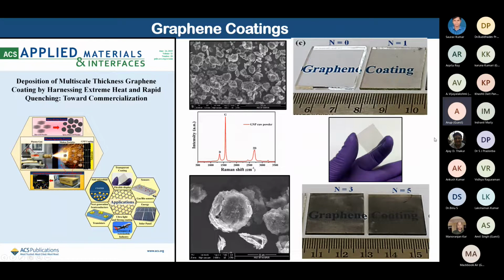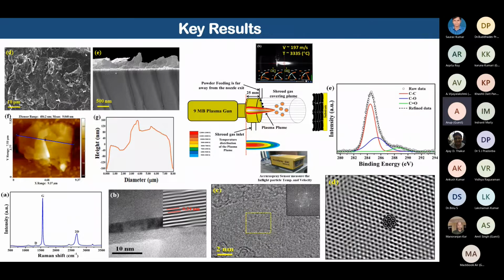So earlier we thought that it would have the graphene coating, but now we have to do the analysis on this. And once we saw it under the FESEM, we found cross-sectional images showing the graphene coating. It is there, and we tried showing it, seeing the patches under the AFM, which shows a height profile of around 320 nanometer. To see the thickness that has been deposited, by doing Raman spectroscopy and by HRTEM analysis, we confirmed that the structure of the graphene has been retained. And then we did the analysis on that. How did it get retained?